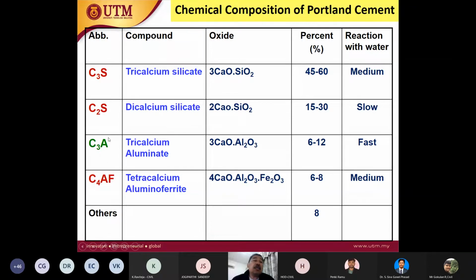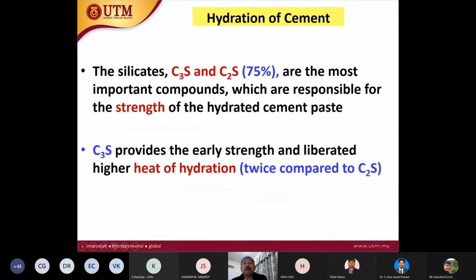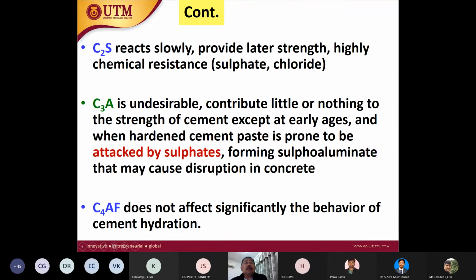So let's say that area contains a lot of sulfate content, so we must make sure that the cement that we select must have less C3A. For example, in a marine environment, we have sulfate and chloride. Sulfate will attack C3A. So this is very important to understand. So the strength will be governed by C3S and C2S. Here C3A is undesirable, but it's there inside our cement, and it tends to be attacked by sulfate. So this is very important.